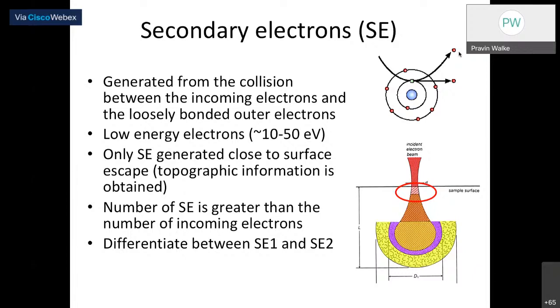And those secondary electrons are usually generated very close to the surface, right? Because the strength of the incoming beam is quite high at the surface level, and therefore there is a possibility of collision of outer bound electrons in the atom with incoming electrons from the electron beam. So this situation of secondary electron generation possibly occurs very close to the sample surface.